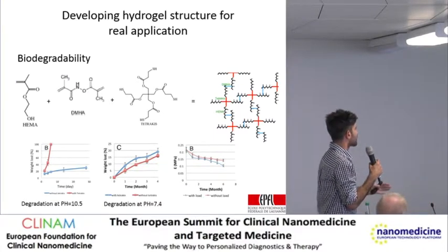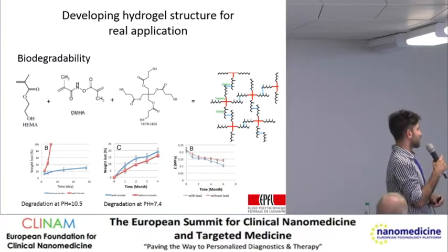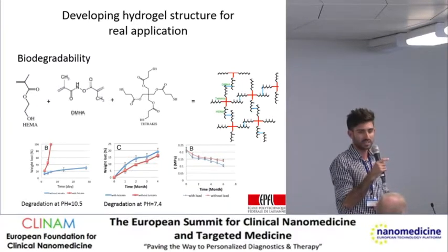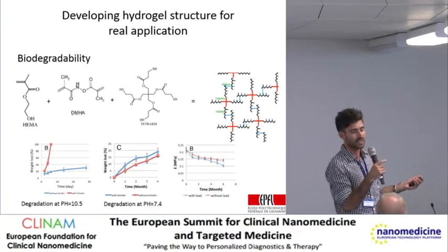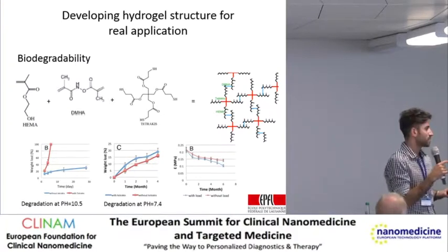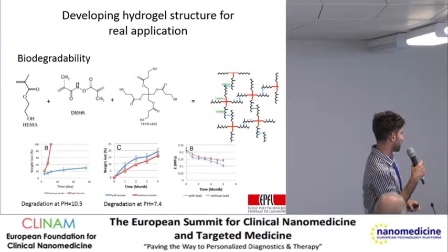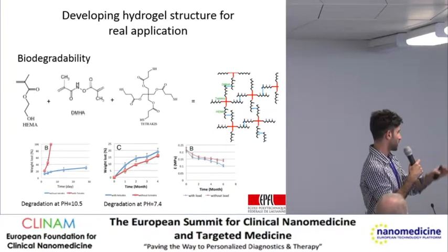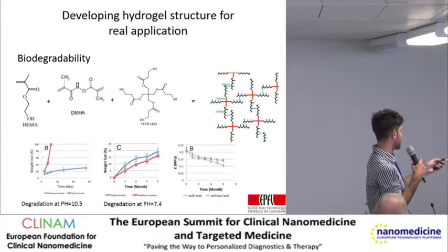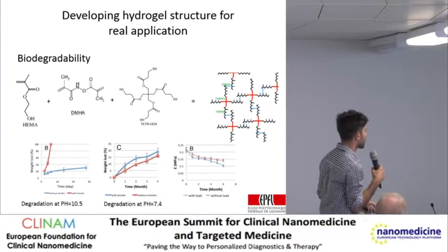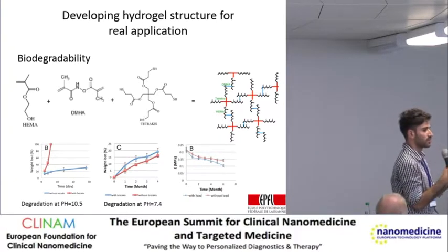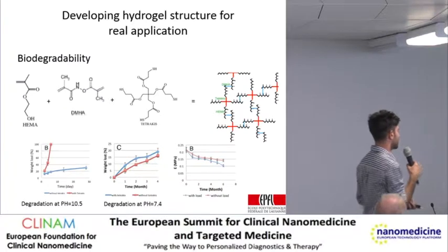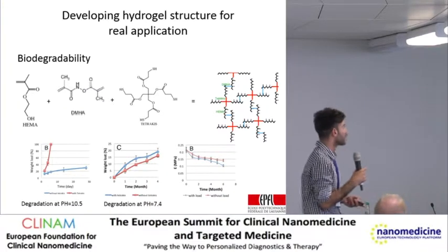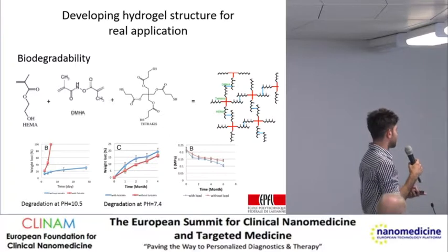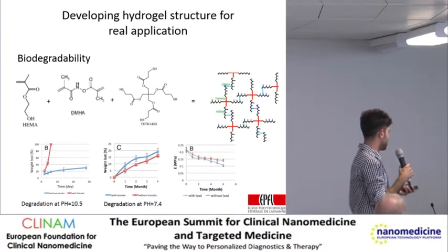We also had a concern about the degradation product, because in this case it would be very long HEMA chains that maybe cannot be absorbed in the body. So I used a tetrafunctional molecule, which breaks the lengths of HEMA. So your degradation product will be a molecule like this, which is a very small molecule. The degradation study is still ongoing, but the first results showed that they had very good degradation compared to other HEMA hydrogels that people introduced before.